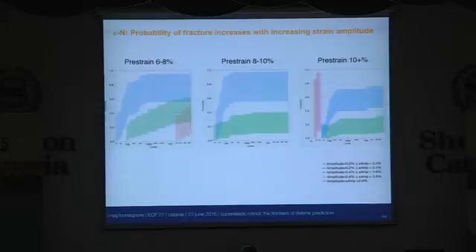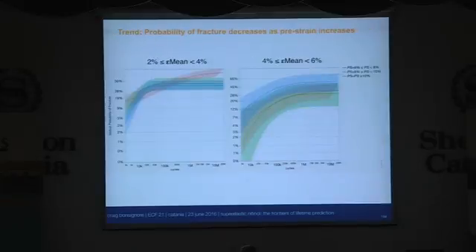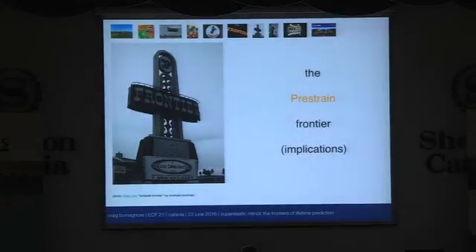So we've tried to do some statistics and take a look at this, and we see these trends. Certainly, we have increasing fracture probability with strain amplitude, but we also see the trend with pre-strain. The statistics aren't super compelling. We've got more work to do, but there's definitely a signal there.